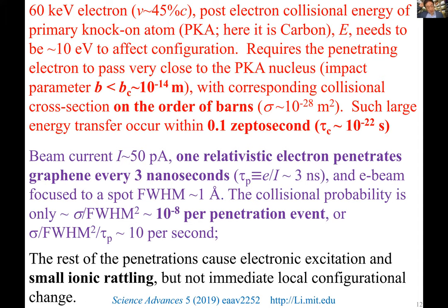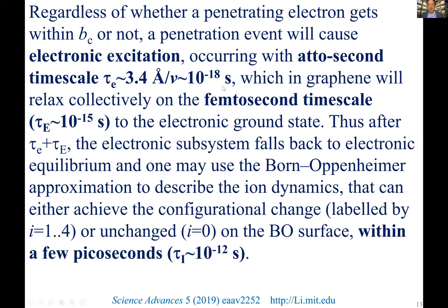The rest will be, it's going to just zip through this 1 angstrom area from the nucleus, and it's going to cause electronic excitation. So that's actually going to drive the electronic subsystem into an excited state, and that later relaxes, but it's going to heat up the ion, and it actually can give the ion a very high temperature. And so that electronic excitation happens at the attosecond time scale.